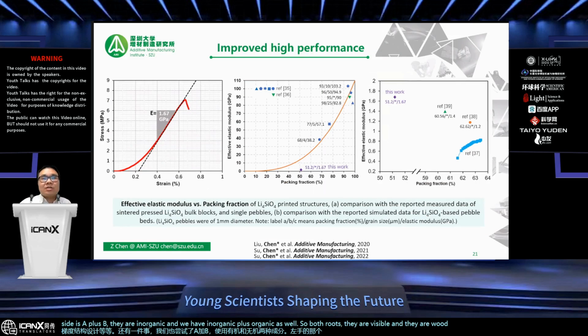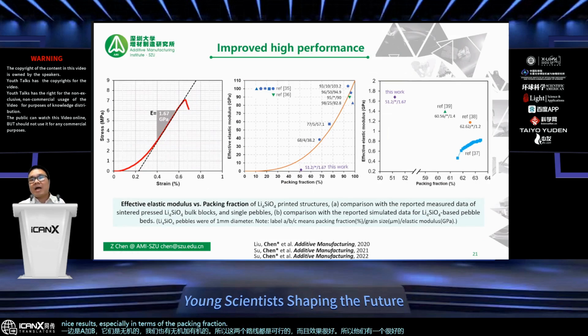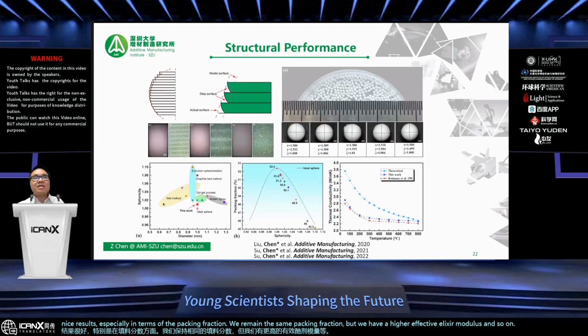They have very nice results, especially in terms of the packing fraction. We keep the same packing fraction, but we have a higher effective elastic modulus and so on. Also we examine the possible influence of the shape. The sphericity for this kind of round shape beads will also be produced, and they have very nice geometric features as well.